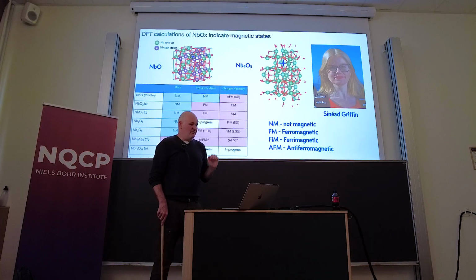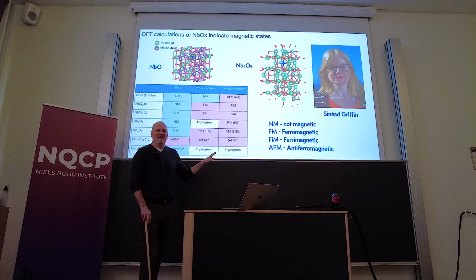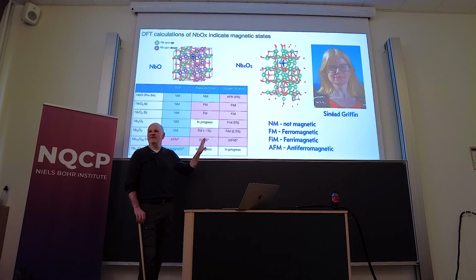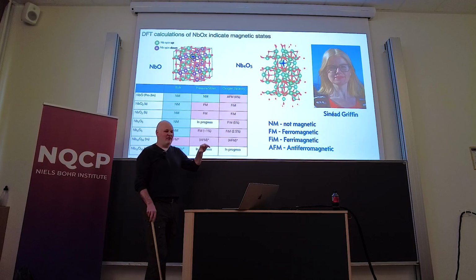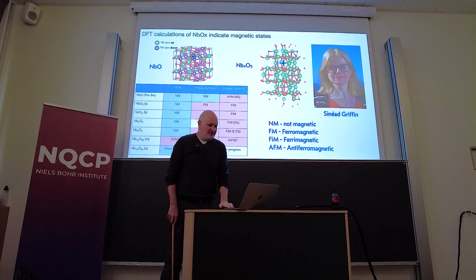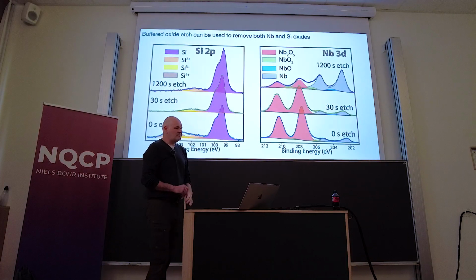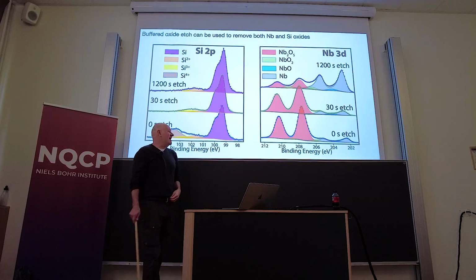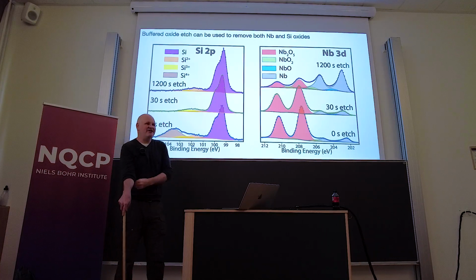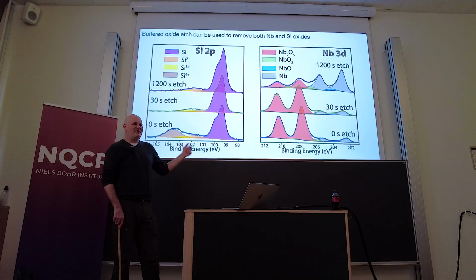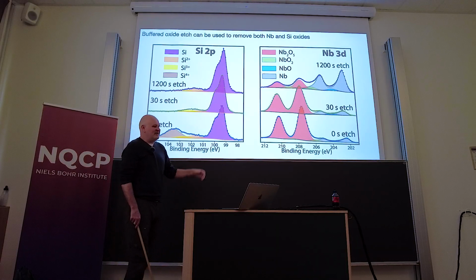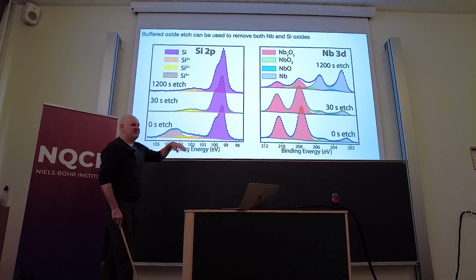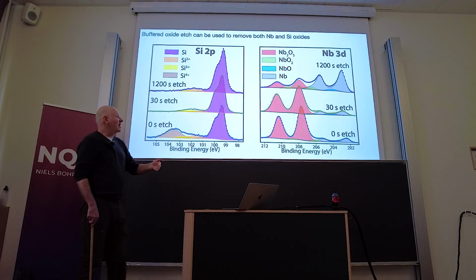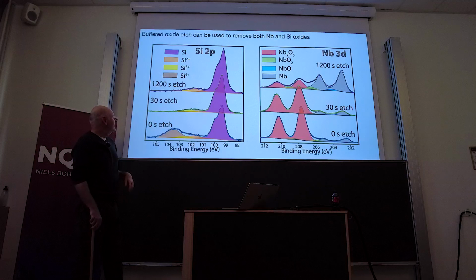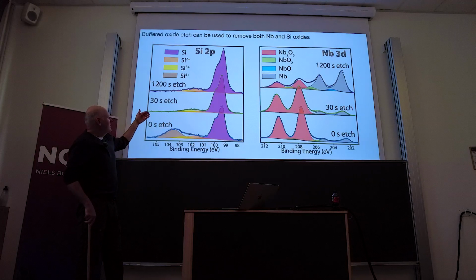And so with this, we thought, okay, maybe we have something here. There's something to the fact that maybe this niobium oxide is not good for what we're trying to do. And so we went about trying to get rid of it. And so the way that chemists get rid of oxides, the first thing you try is HF, which is what we did. It turns out HF is pretty good at dissolving niobium oxide. And so here you can see 3 different time steps where we've dunked these chips into buffered oxide etch, which is essentially HF, and with XPS measurements at these different time points.